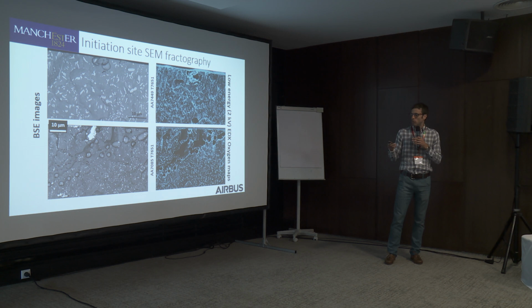So we've really got good evidence that there's water at that initial initiation site, and that it is retained for some small periods during the short crack growth. But later on the water has disappeared, and we only see oxidation of the surface, and we don't see any more evidence of crack arrest markings and this elevated oxygen signal.